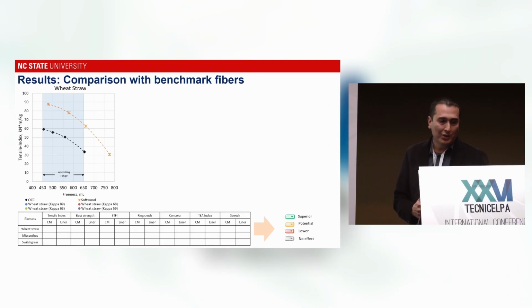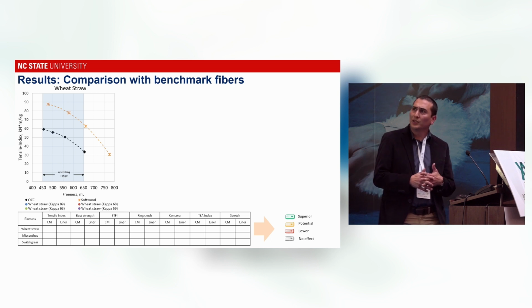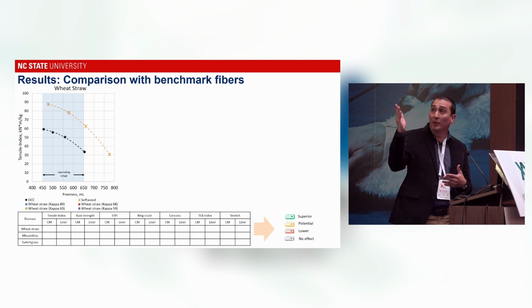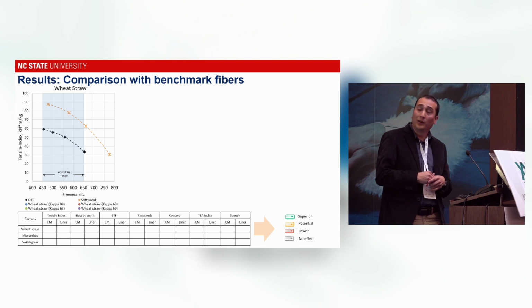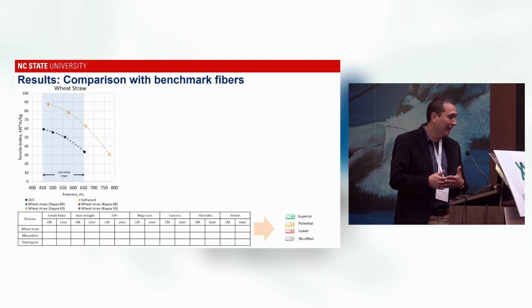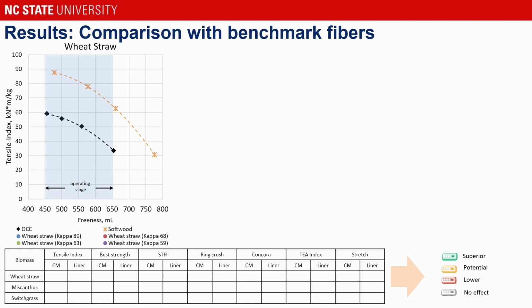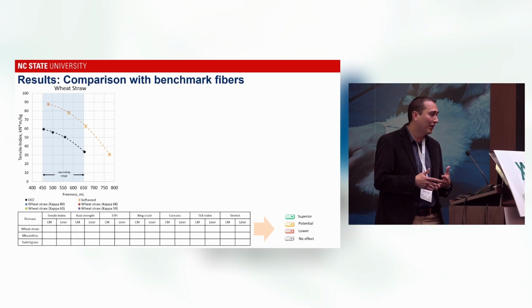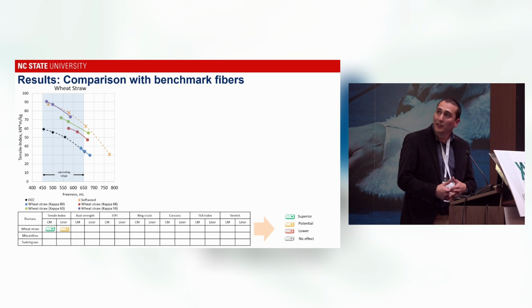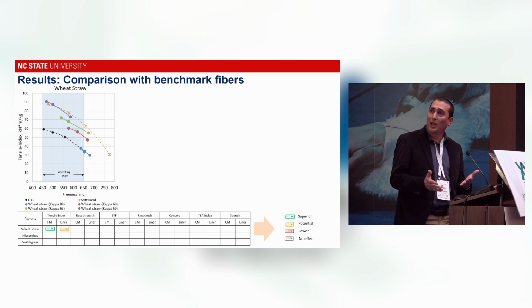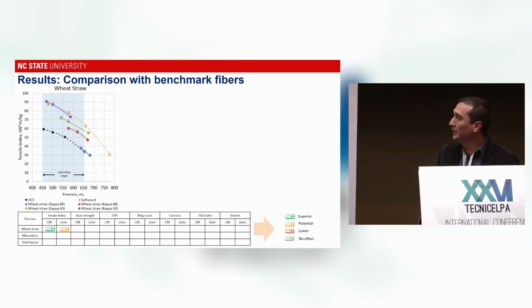Because we are short in time, I would like to show just a quick summary of the result that we already got. So in this graph, you can see, for example, for wheat straw, we are doing the comparison of the tensile index for conventional fibers such as OCC, which means old corrugated container board, and we also compare this property with softwood, which are common raw materials for liner and corrugated medium. And something that is interesting here is that when we change the cooking time, we can obtain similar properties to OCC and even close to softwood fibers.